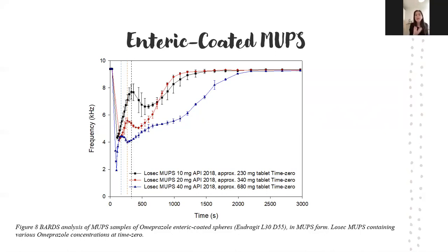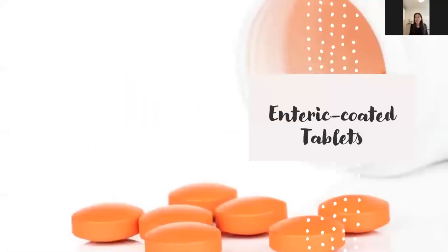So the first event is that pink outer coating that encompasses those microspheres erodes and releases the pellets coated in Eudragit L30D55 into solution. And our second event, marked by that dashed line, relates to the erosion of that enteric layer and subsequent disintegration and deaggregation of the spheres. So the hydroxide actually perforates that outside coating and a hole appears in that pink coating. So there's actually a microsphere released from very early on, hence why we don't get a true lag time in this dissolution profile. So we go into enteric-coated tablets, same as our microspheres, just a bigger tablet size.